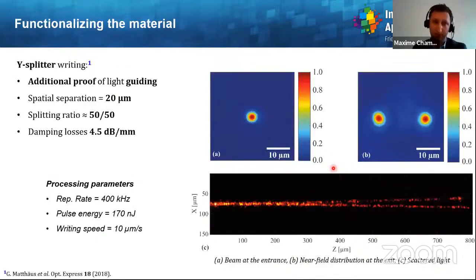Again, it was possible to demonstrate some functionalization of the material with a Y splitter, so a multiplexer, which is actually an additional proof of the light guiding. Here you can see the beam before it enters the waveguide, and here is the near field image, which corresponds to the measurements, and you can clearly see two different spots corresponding to the two different parts of the Y coupler. So the splitting ratio was 50-50, and here again the damping losses were 4.5 dB per millimeter.